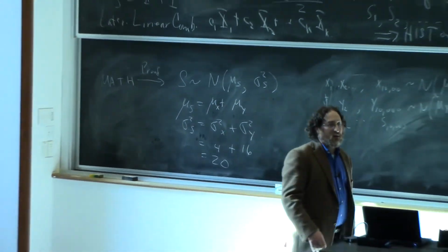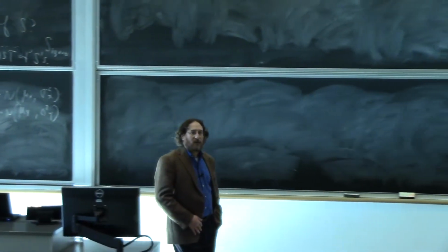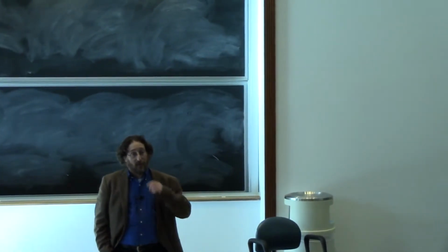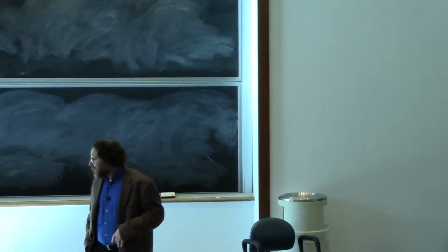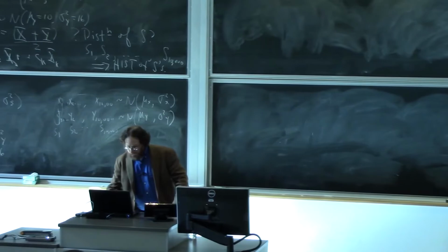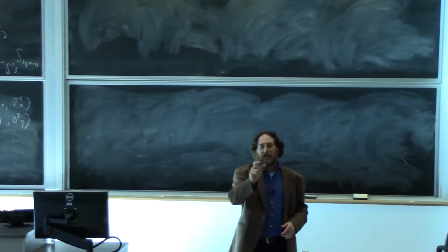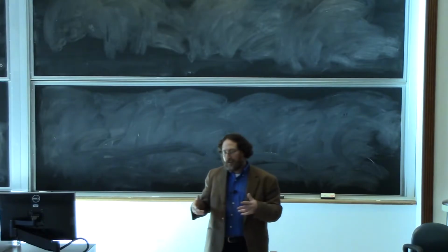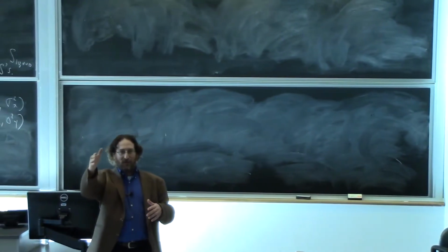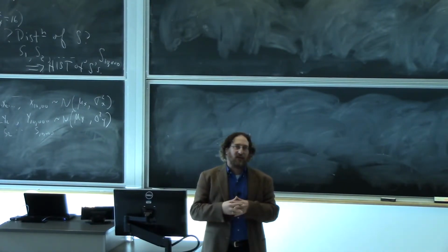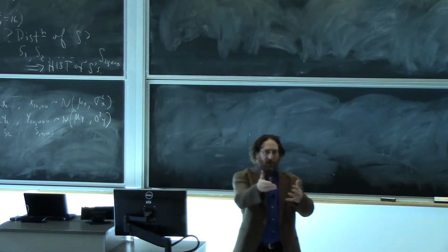Good. In the derivation for the change in resistance, you have this alpha parameter. Do you have any physical limitations? Yes. So alpha is known as the Bruggeman exponent. I won't flip all the way back to it. Alpha really is the exponent that relates porosity to tortuosity, and tortuosity is a measure of how tortuous the path is that something has to diffuse through. So this alpha is kind of a scale. It's an empirical number, if you will.